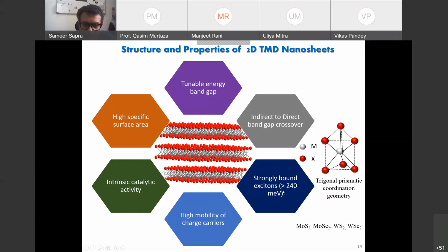The excitons are very strongly bound because they have to move in these sheets, and I'll tell you how strongly bound these are. You've already seen the excitonic peaks in the absorption spectroscopy. If they are observed, it means they are definitely more strongly bound than room temperature thermal energy. Then you have a high mobility of charge carriers, high specific area, and because of the high specific area, you also have high catalytic activity. So a lot of applications based on all these properties can be thought of. This is typically the trigonal prismatic arrangement that I'm showing again over here, with molybdenum in the center and the chalcogens around it. So you can think of a lot of applications.